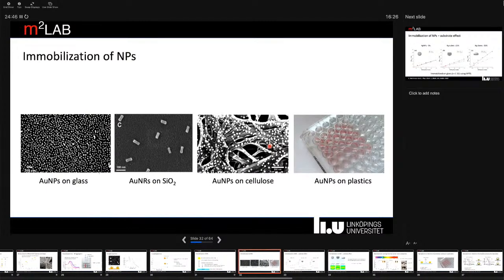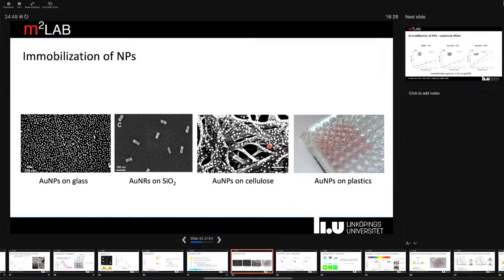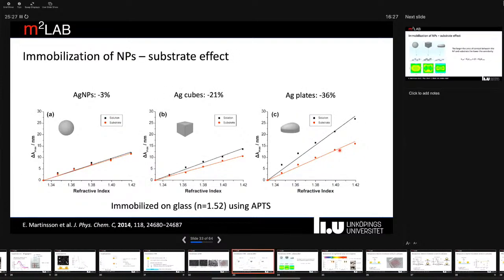And these are some examples of sensor surfaces that we've been working with, primarily quite a lot with gold particles on glass. This is what it can look like in an electron microscope, or gold nanorods on plasma treated silicon oxide, or gold nanoparticles adsorbed to a nanocellulose substrate, or gold particles immobilized on a plastic substrate. So there are many options here. Depending on your application or what you want to study, you can essentially pick and choose whatever substrate works for you. But there are some things you need to take into account when choosing the substrate-particle combination.